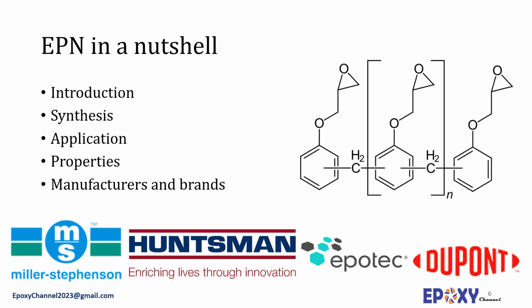The family of EPN resins have various properties, but the common ones could be viscosity at 25 centigrade between 600 to 50,000 centipoise, epoxide equivalent weight between 160 to 270 grams per equivalent, functionality 2.2 to 3.8, color 1 to 3 on the Gardner color scale. Some EPN products in the market include Aditya Birla Group Epotec YDPN, Miller Stephenson Epon SU8, DuPont DEN 42 or 3X, for example 424, and Huntsman Epalloy.